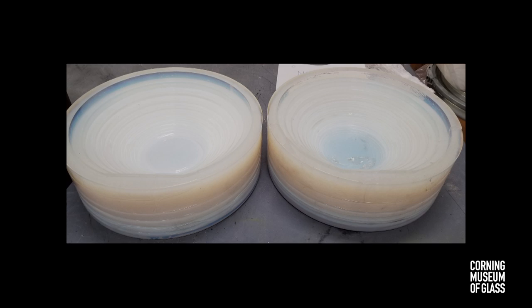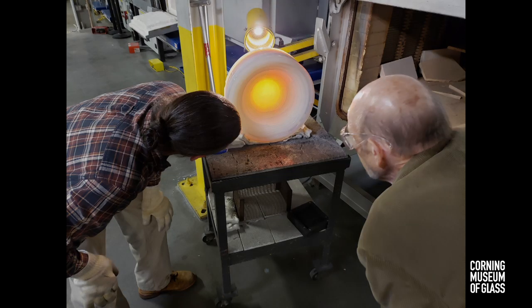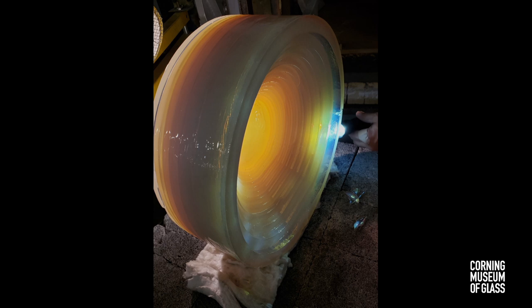There was an increasing belief that the biggest problem was the graphite mold. Down in North Carolina, Jake and I have developed vermiculite molds that are more insulative and have other advantages for casting opals, but they are not reusable. We never got a piece made during our residency. The good news is Corning is going to release the glass that Jesse developed to the studio world. I believe with the utilization of other mold materials, stunning results are possible. Later this year, I am planning to test lowering the temperatures even further and increase the workability. No doubt there will be frustration and failure in that effort as well, but it might succeed.